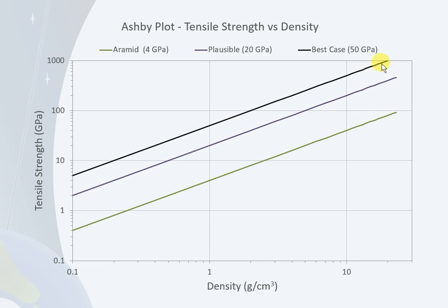And I've got this one other case, which I'm simply calling my best case scenario, and that's at 50 gigapascals per gram per cubic centimeter. At that point, I think that's about the best that known materials as well as near-term research materials are going to achieve. That assumes some of the highest tensile strength we've ever observed, as well as some of the lower densities. Not the lowest by far, but the highest strength and the lowest density pairs that we've seen.